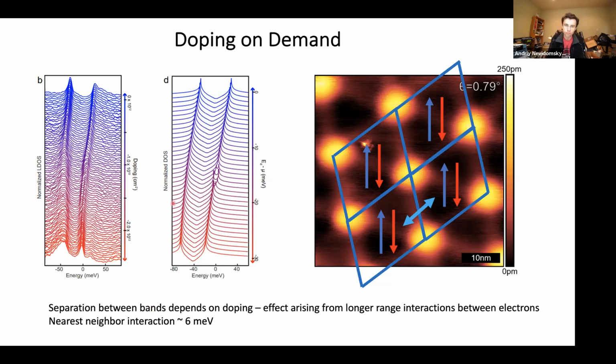Thank you, Andy. And you're absolutely right, one expects to see a real gap between the first subband and the higher subbands. But in a spectroscopy experiment like this, you always have inelastic processes that obscure that gap unless that gap is really at the chemical potential. So there are people, not me, who have doped it exactly to the chemical potential, and then you can see that gap more clearly.